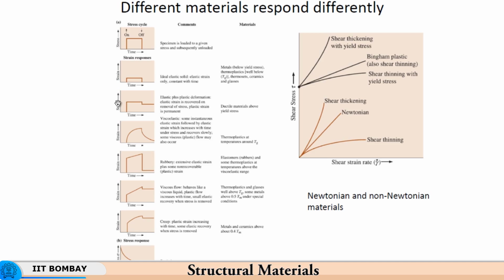So, elastomers, rubbers, and some thermoplastics at temperatures above the viscoelastic range result in this kind of behavior. So, this way one can go on understanding the behavior of different materials. You have another material like thermoplastics and glasses well above the glass transition, and metals above 0.5 Tm under special conditions. So, here you have what is called an immediate increase in the strain rate, and then you have the hardening of the material due to strain rate. So, here you have hardening due to the strain rate increasing due to viscous effects.